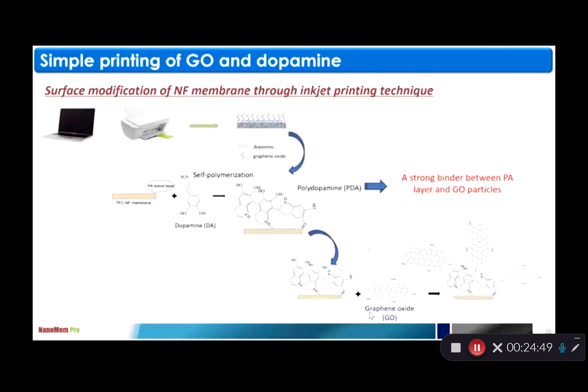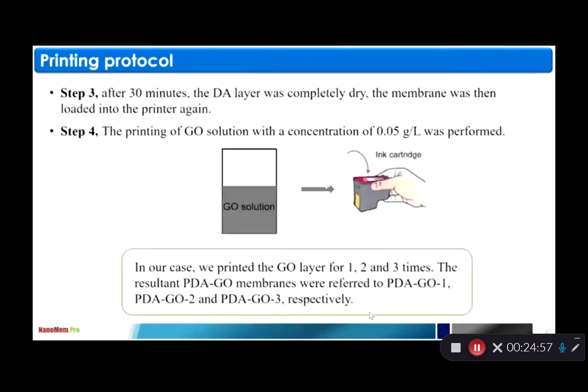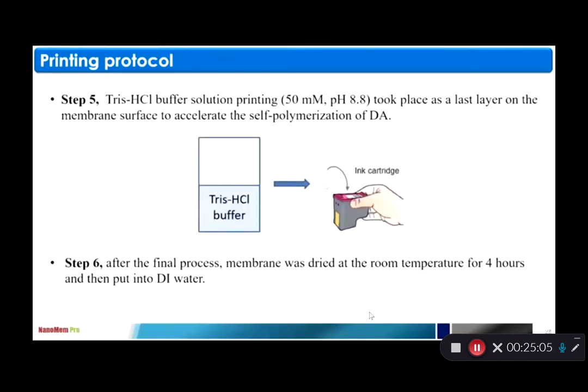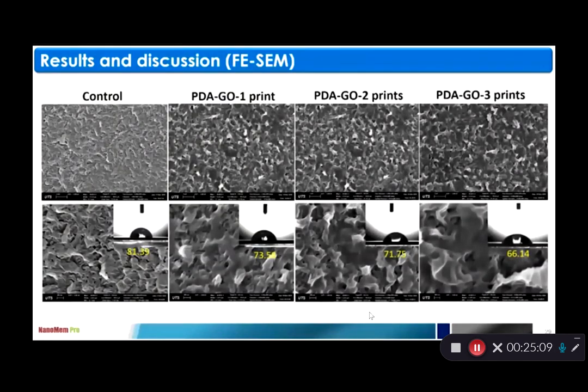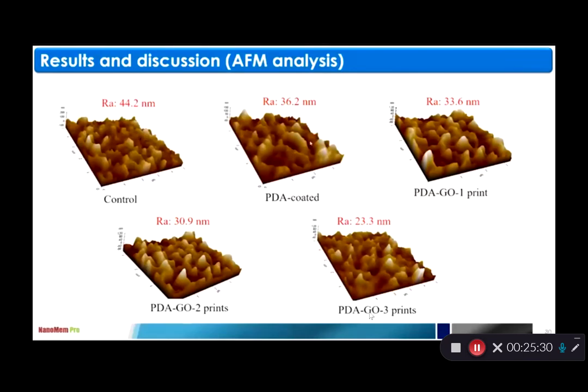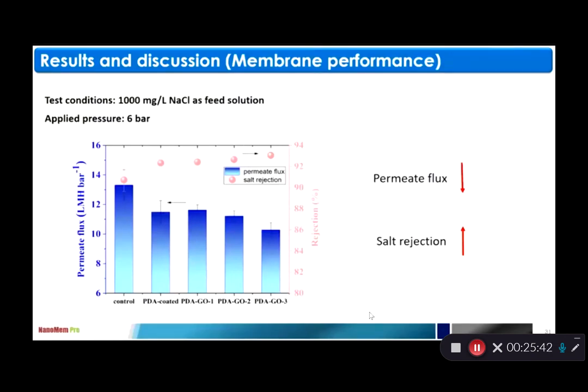So this is very much similar to what I already explained. We just changed to graphene oxide in the inkjet cartridge, and we just printed this material with the graphene oxide, with different cycles, to see how this changed the overall performance of the membrane. So this is the graphene oxide. We have 1 time and 3 times print. And then you can see the control, and then they changed the morphology, and also changed the contact angle from 81 to 66, less hydrophobicity. And then the roughness also changed from 44 to 23 nanometers when you have more cycles of the graphene oxide layer. And then we try to compare the overall change in permeate flux and rejection.